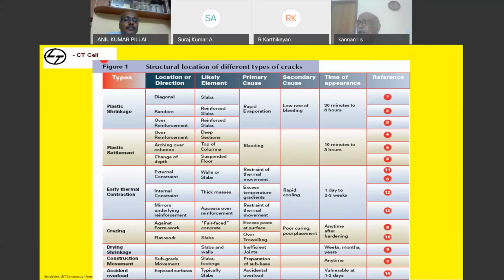Crazing can happen. Suppose you have done a smooth finish, power trowel finish, and the curing is not done properly on the floor. What happens is the floor will have very, very minute cracking. After 10 days, if you pour water now, you can find all these octagonal cracks on the floor surface. These are all crazing cracks. Okay. Then drying shrinkage, it can happen any moment, weeks, months, or years together. Even after 1 year also it can happen.